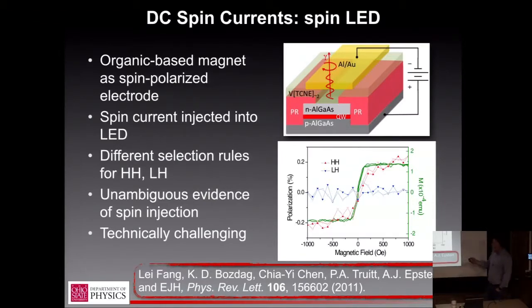So there's a lot that I'm not talking about, the control measurements and all this, but basically if you look at this red data here showing the polarization of the heavy hole luminescence line, it mimics very closely the green data, which is the hard axis magnetization of the V[TCNE]. So this is one demonstration from our group, and not that this is unique, that you can start to develop organic spintronics on the same pathway as inorganic spintronics.